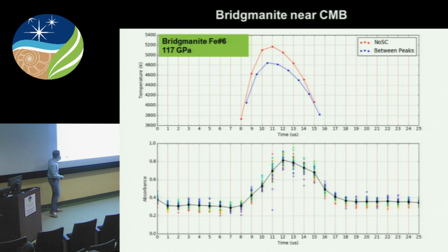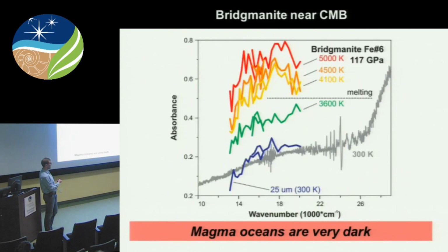So you can analyze these images in a different way, and I have to say that Nick has been of great help in providing a very clever way of how you can efficiently analyze such images for spectral information. What you can see here is just absorbance as a function of time, but the different colored circles show you the difference in absorbance at different wavelengths. So red is red wavelengths, blue is blue wavelengths. You can see that before laser heating, the sample absorbs red light less than it absorbs blue light. At high temperature, that sort of gets messed up, but then you quench it again to a spectrum that has a positive slope and absorbs less of red light.